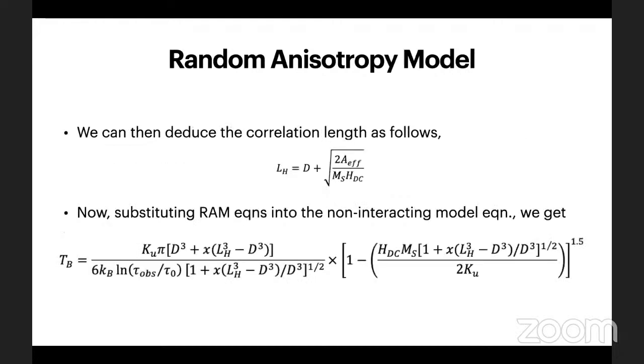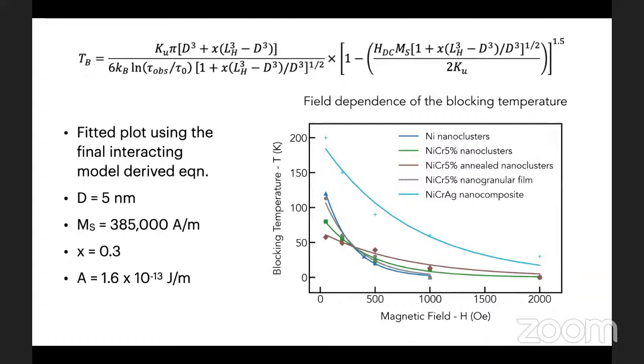Then, using the interaction intensity, we deduce the following equation for the correlation length as a function of H. Now, we substitute all these into the non-interacting model to derive an equation that is purely based on the coupled interacting particle model. Using the above derived equation, we fit our data with the following experimental parameters and establish the value of the uniaxial anisotropy for all our values.